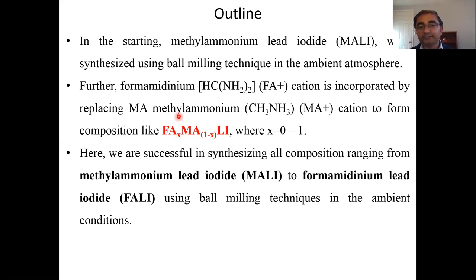By changing the FA content, we can change the band gap of these materials. And if we change the band gap of this material, we can tune it, we can play with the band gap, and we play with the photovoltaic properties of this material. And that is the beauty of this material. But the problem is to synthesize this material. It degrades in the environment.